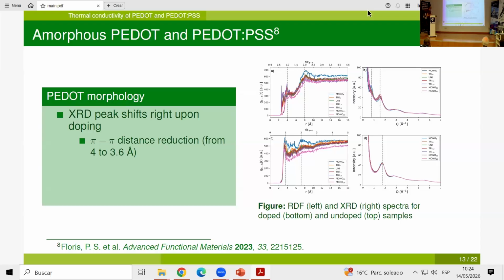We also measured the X-ray diffraction peaks of undoped and doped PEDOT. Here is the undoped, and we measured a pi distance of 4 angstrom, and upon doping, it shifts to 3.6. This doesn't really have implications for thermal conductivity, but it probably does for electrical conductivity, since it could increase the electron tunneling probability.